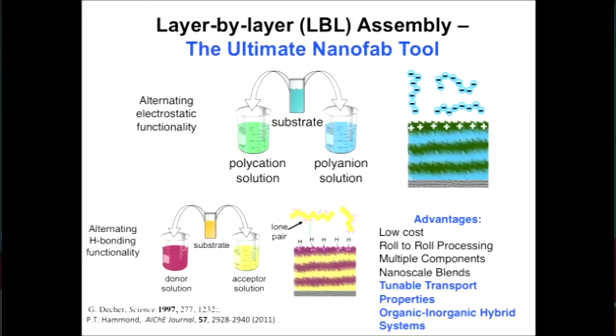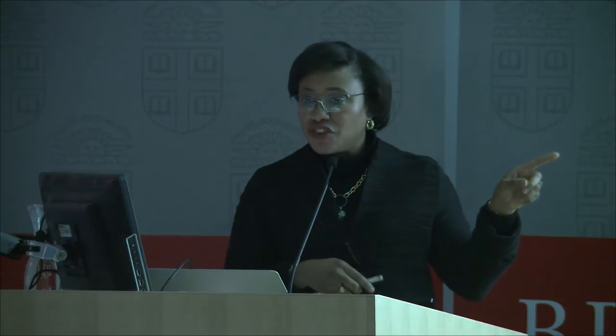You can rinse anything that's not truly adsorbed and now dip it into another water solution that contains a negatively charged material. So back and forth, you can adsorb positive, negative, and build up these alternating layers, sandwich style, in which you control what goes into the film as long as you maintain plus minus alternation. This means that you can generate layers which contain different things as long as you follow the rules. You can do the same thing with hydrogen bond donors and acceptors.